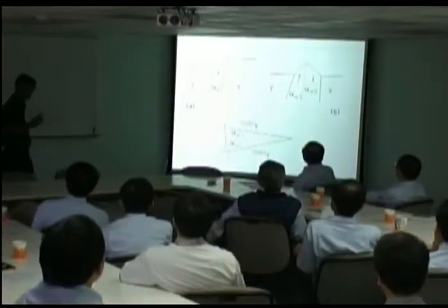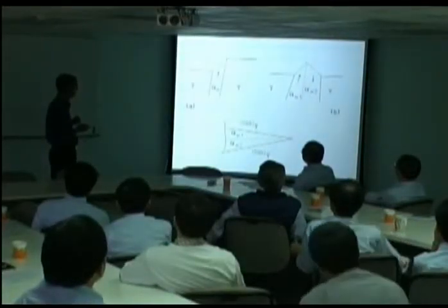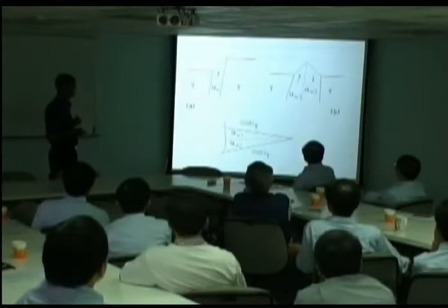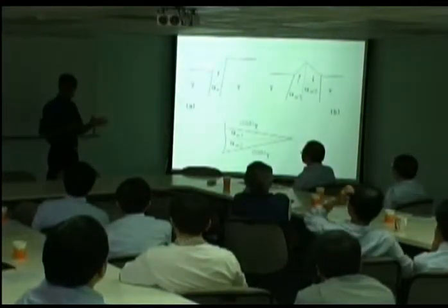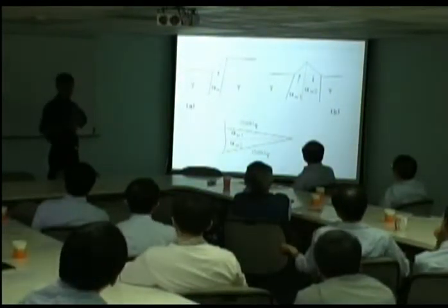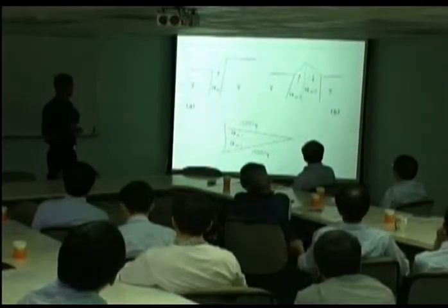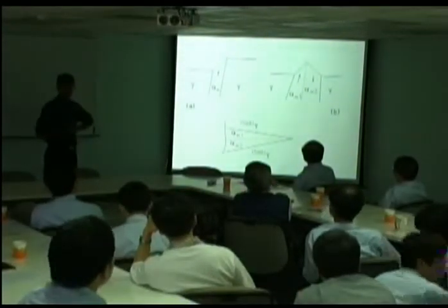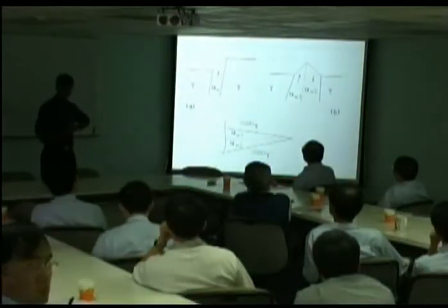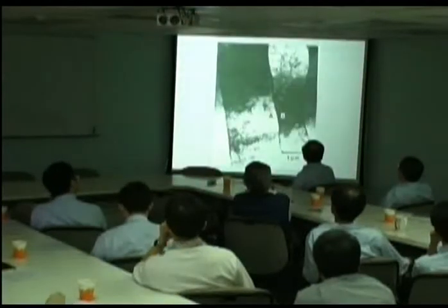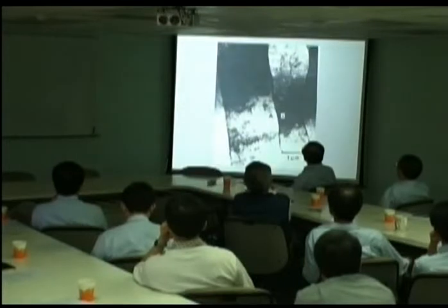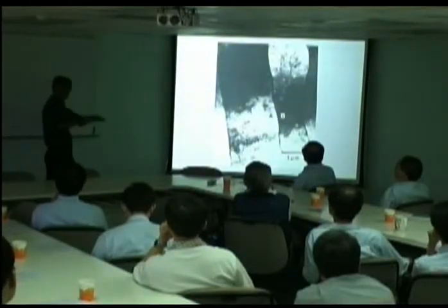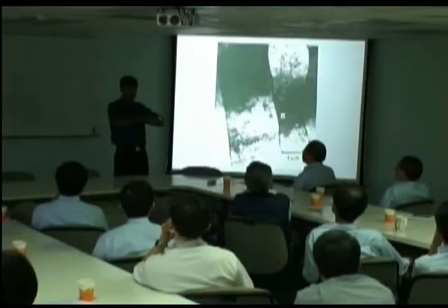The axial shape change is slightly complicated. This is what we expect with martensite or bainite. But this is what we get with Widmanstätten ferrite. It actually consists of two plates which are compensating each other by shearing in not exactly opposite directions, but different directions. Because these are two different crystallographic variants, you get this thin wedge shape, because this is a different plane from this. And we should have a boundary in between those two planes. And indeed, when you look in a transmission electron microscope, you find the boundary in what optically appears to be a single plate. So it's a very clever transformation that it cancels out the strain energy by two plates forming.